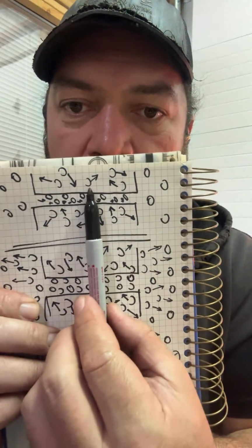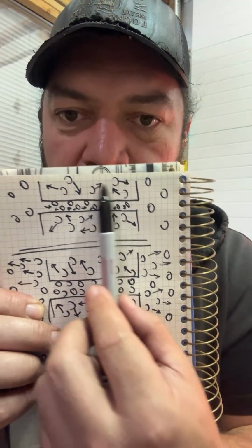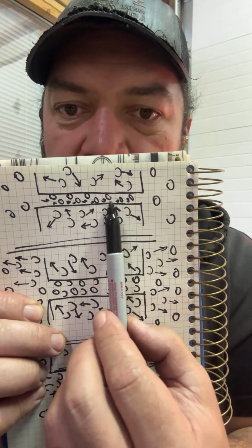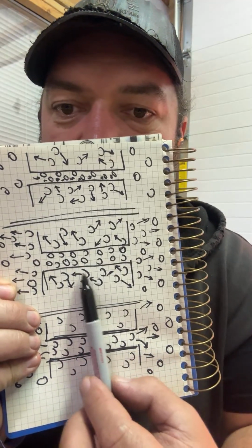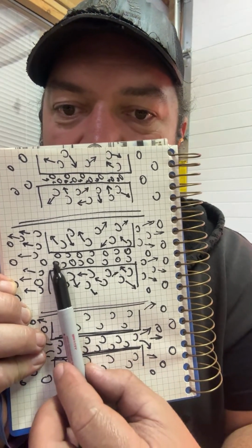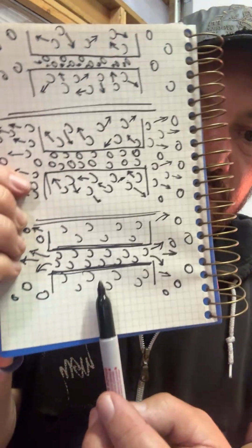That free carbon that's escaping the steel is also leaching onto the oxide connected to the iron that is between those layers, and is also cleaning away that oxygen, leaving behind pure iron. So with time, you are allowing your steel to self-clean. Again, it starts out with oxygen in between the layers, this carbon, the oxygen on the outside. But as you start to heat it up, the carbon starts moving around, and eventually the carbon starts leaving the steel. Now, initially, there's going to be some oxygen in here, but eventually, with time, there's going to be no oxygen, including the oxygen tied to iron oxide, and that steel will self-clean.